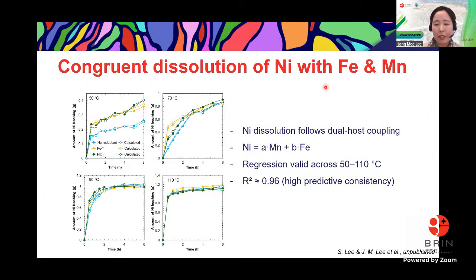So based on the assumption that the nickel will be dissolved from the iron phase and also the manganese phase, we did a congruent dissolution study based on the previous kinetic study, the leaching test, to see the kinetics. We did a regression equation, and then we found the nickel dissolution follows the dual host of iron phase and manganese phase coupling, and across all temperatures, nickel dissolution can be described as a linear combination of manganese and iron dissolution.